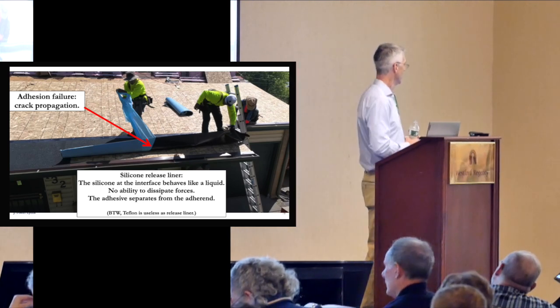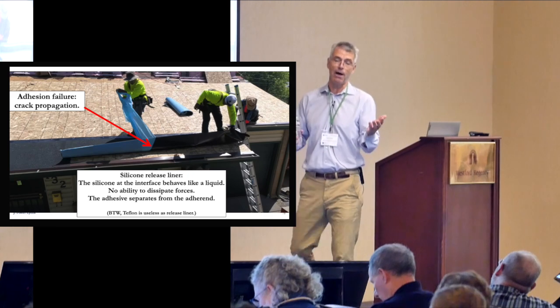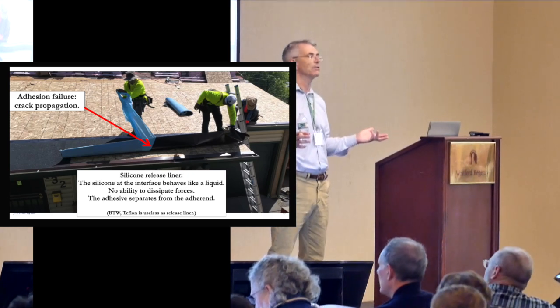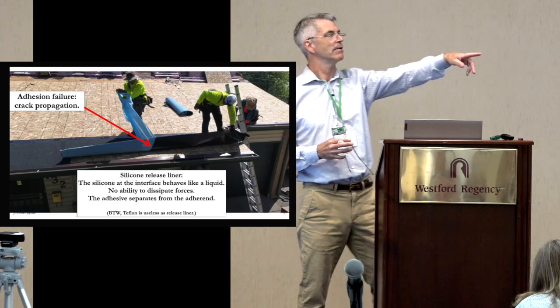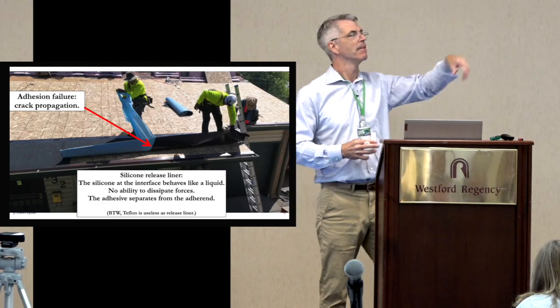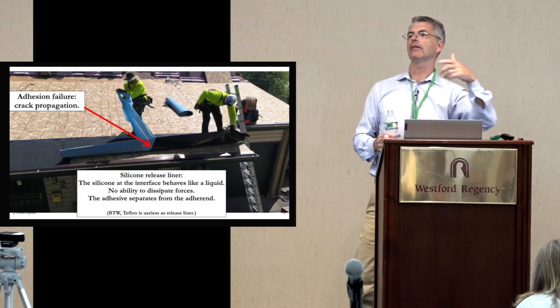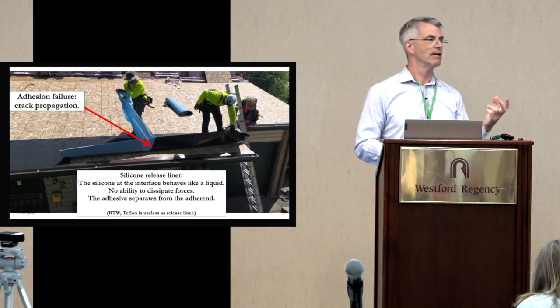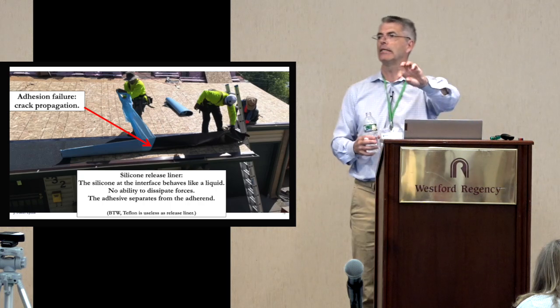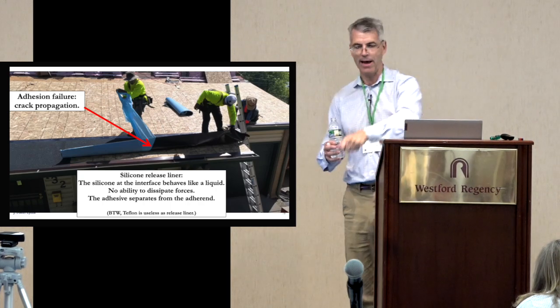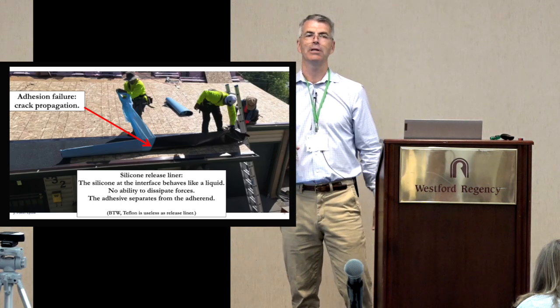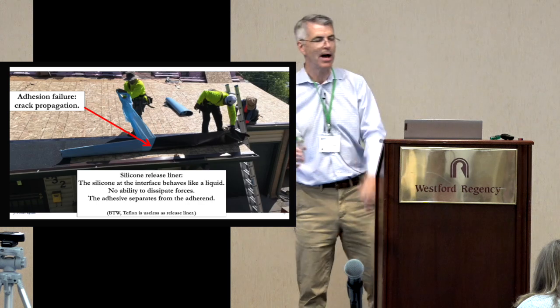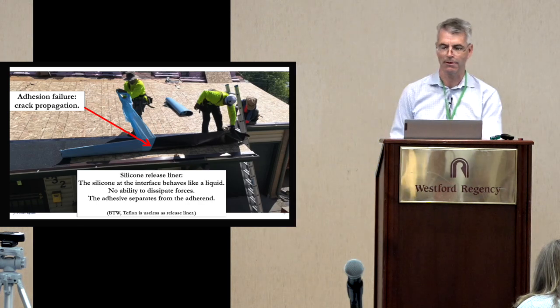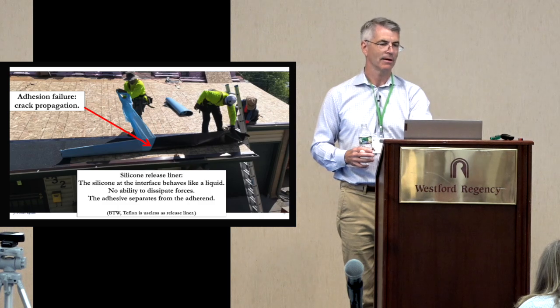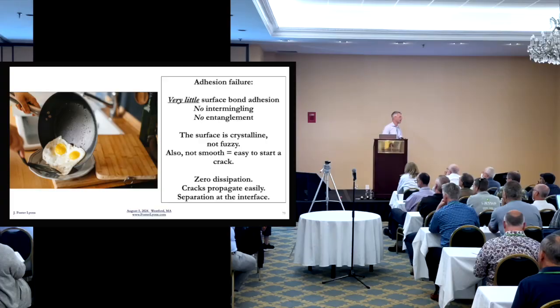And the reason we use silicone materials rather than Teflon, because you'd think, wow, Teflon, right? The crappiest surface energy in the world. Why don't we use that? No, the reason is the same as with the pan and the tape. What's going on at the surface, there's a particular property of these silicone materials that doesn't exist in the Teflon materials. They actually behave like liquids at their surface. So as you apply force, the point at which the force is applied behaves like a liquid, not like a solid polymer. So they just peel right off. Teflon wouldn't do that. It's completely useless as a separation material. I already talked about the pans, so there's no intermingling, no entanglement, so there's no fuzz, and that's the reason